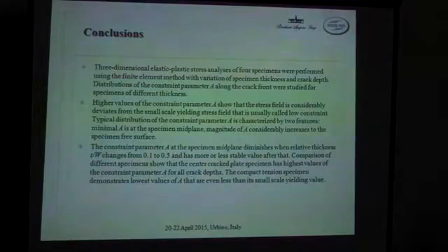Comparison of different specimens shows that the center crack plate specimen has highest values of constraint parameter A for all crack aspect ratio, and CT specimens demonstrate lowest values of A that are even less than its small scale yielding value.